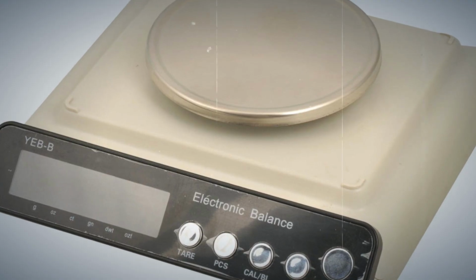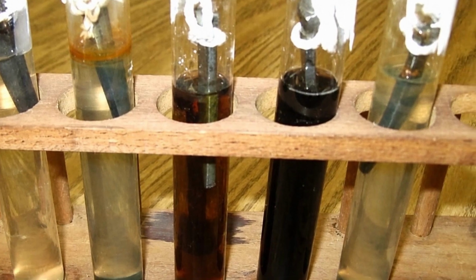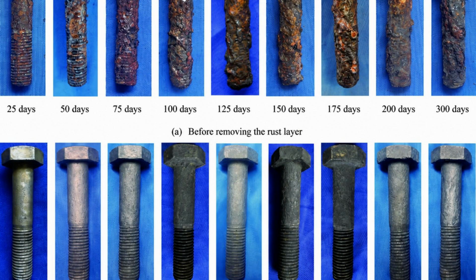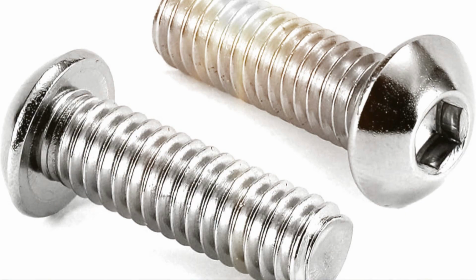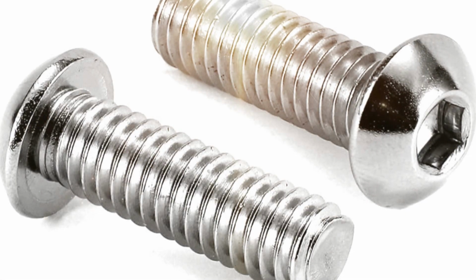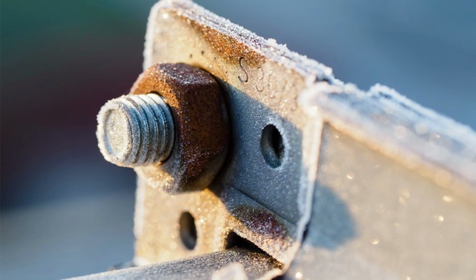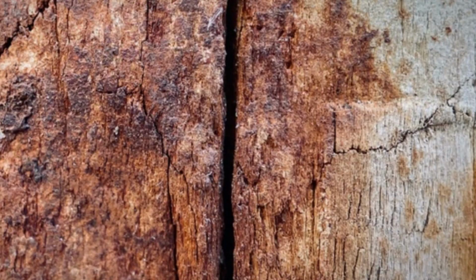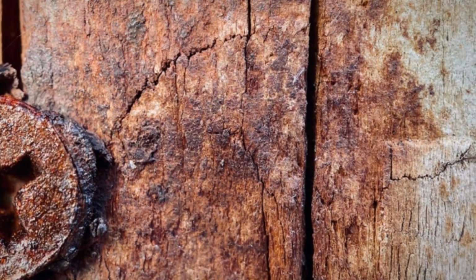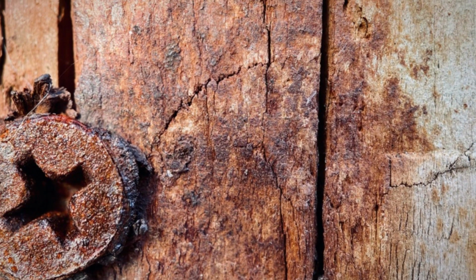The numbers are not subtle. Laboratory testing showed standard zinc-coated fasteners lost more than half their mass after 1 year in copper azole solution. Stainless showed negligible loss. Electroplated screws now fail in 1 to 2 years. Ordinary interior screws rust out in 2 to 5, and the board splits around the corroded shank.